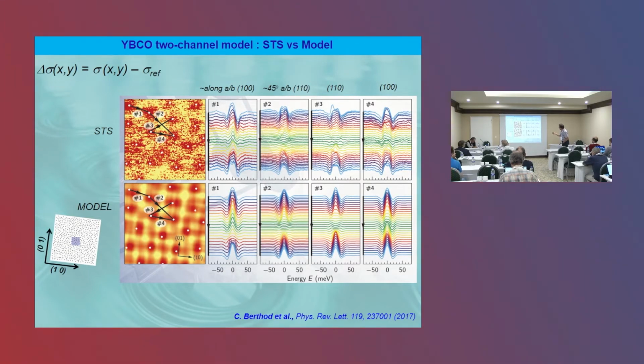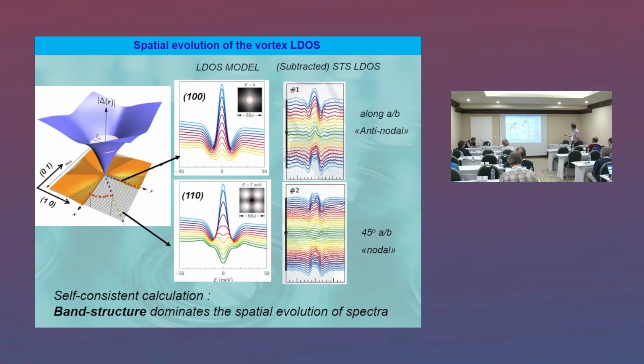I would like to focus your attention on the different crystallographic directions. These are the traces taken along the 100 direction, while the other one here at the center is along the 110 direction. You see that the decay of this anomaly is not the same in the two directions, and the model also predicts this. This is a self-consistent calculation. You see that the decay of the zero bias anomaly along the 100 is slower than the one taken along the 110 direction, which is the nodal direction. This behavior essentially comes from the band structure, with the Fermi velocities, which are anisotropic and determine this behavior.